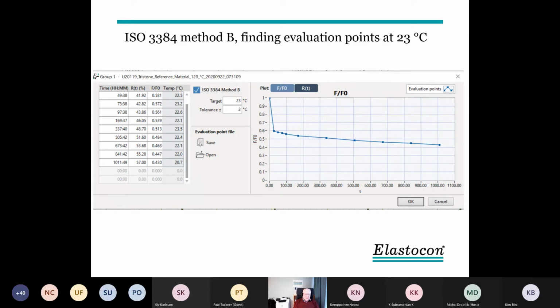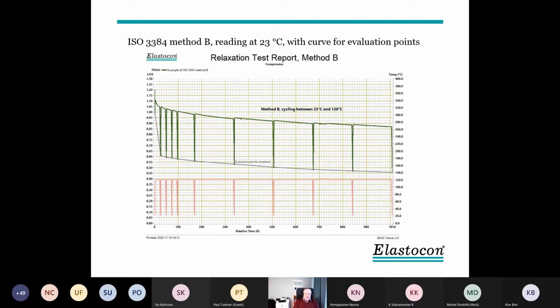Then we can get the plot of the force at room temperature, change in force. Then you can plot the report looking like this. Here we have, say, when you run method B, you always start at room temperature. You get the original F0 value, if it's possible to see here. So the test starts there.